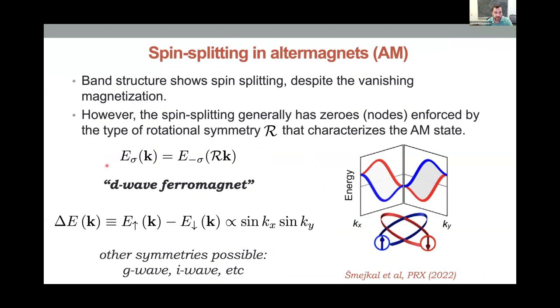And the key point now is that spin degeneracy of bands is no longer guaranteed. In fact, bands of opposite spin are related by rotation. So generically, actually, you're going to have a splitting between spin up and spin down, except along the directions or planes that are kept invariant under the rotations. So the general consequence of that is that your Zeeman splitting or your spin splitting will have nodes. And for example, you could have nodes that are along the main axis.